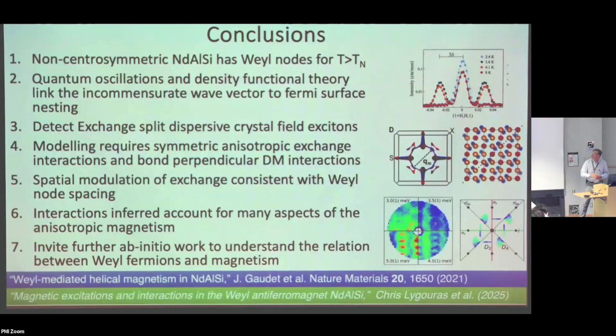So just to conclude, we've been interested in what is special about the RKKY type interactions mediated by Weyl electrons. They're very anisotropic, and they induce a DM interaction that in turn induces a non-collinear modulated spin structure. And we've been able to actually extract all of the interactions, and we are hoping for a continued engagement with theorists to understand really the nature of the interactions mediated by topological electronic band structures.